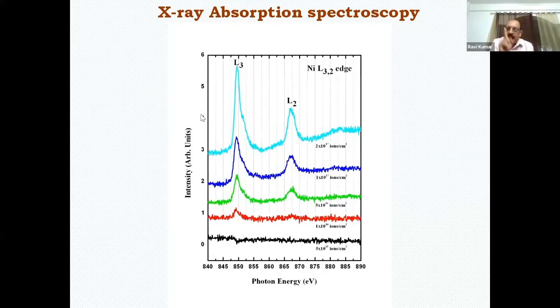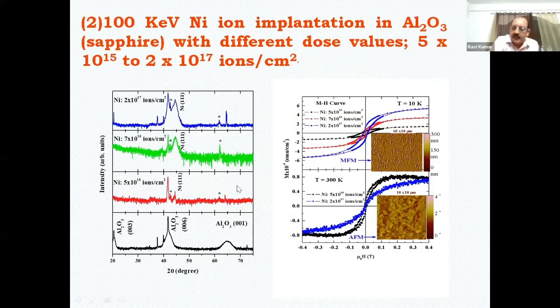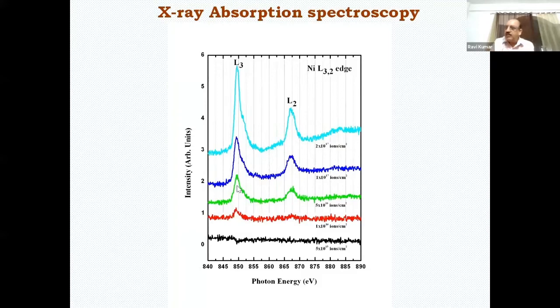Then we go to the nickel element-specific measurement, to see whether they have a nickel oxide structure or a nickel metal structure. If there is a nickel oxide structure, the d orbitals will split with the oxygen interaction, and this crystal field splitting will take place and give you the multiplet structure. Here we have not seen a multiplet structure. You can clearly see a single L3 and L2 edge.